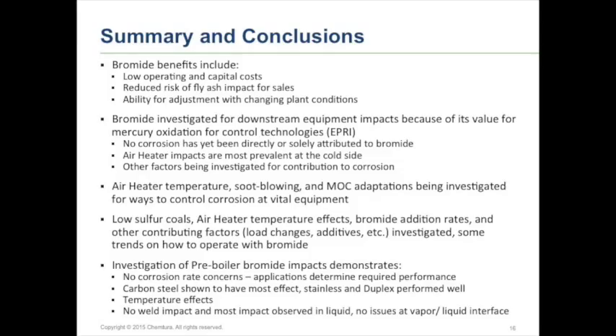Bromide is being investigated, and there's still more work being done. I'm sure more reports will come out, so keep your eyes open for those; there's more data coming out every day. Nothing has really been attributed totally to bromide. There are also other things going on in the plants, with indications that it could be temperature and just dealing with a different environment as far as what you have coming out of that boiler. Air heater temperature is a big focus, and soot blowing if you're adding carbon upstream, as well as enabling your baskets to do some things around the materials of construction, could also help with any issues you might see.